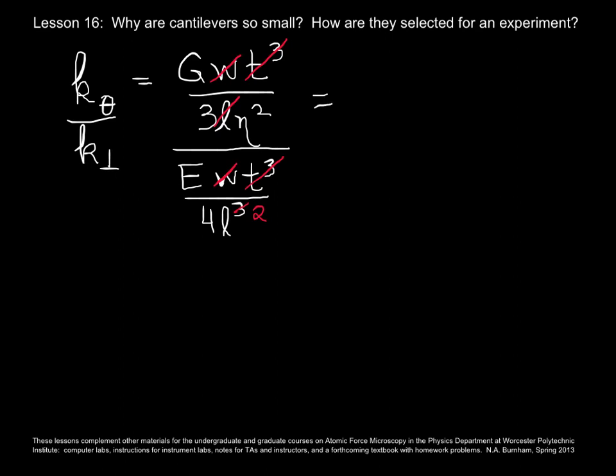And so we simplify this down to 4 shear modulus over 3 times the elastic modulus. That's controlled by the selection of materials, silicon or silicon nitride typically. And then we have the length over the tip height squared. So that means if you were looking for a cantilever that was stiff torsional and compliant normally, you would want one that is long and yet has a short tip. And then you can do similar kinds of calculations for other experiments that you're considering.